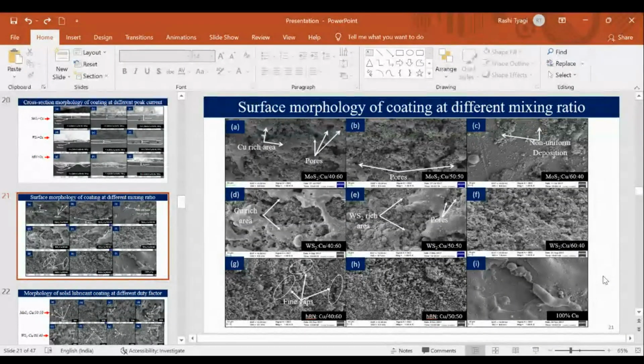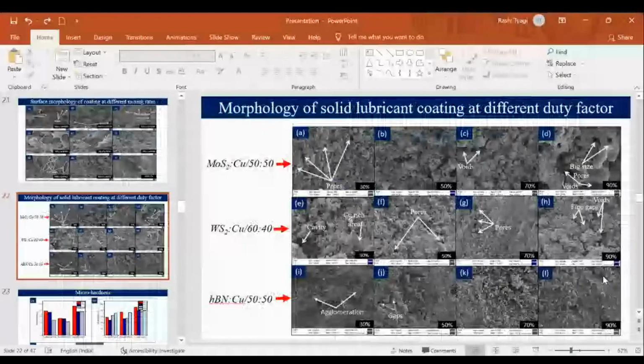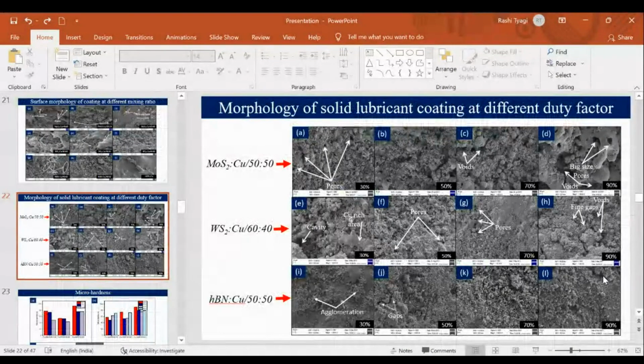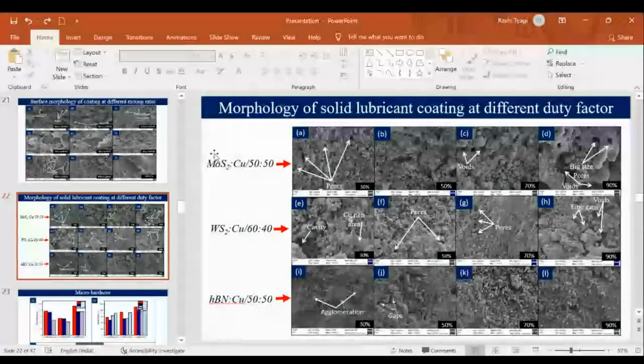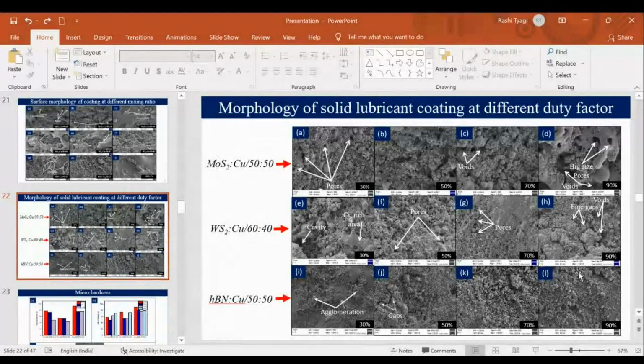So we can say that by using a different mixing ratio, we can find the particular powder composition at which we can reduce the porosity in the coating. This is the morphology of the solid lubricant coating at different duty factors: 30, 50, 70, 90. Duty factor basically defines the efficiency of the process. Duty factor defines the cycle in which pulse current goes through the tool and melts it and deposits it.